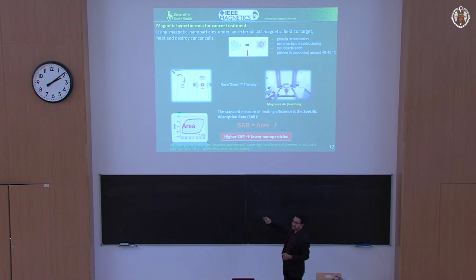We have to generate a large amount of hysteresis, loops like this. This is the AC hysteresis loop. Please do not confuse this with the DC magnetization that you measure in a SQUID. Remember, these are small particles, superparamagnetic particles. There is no coercivity, there is no hysteresis.